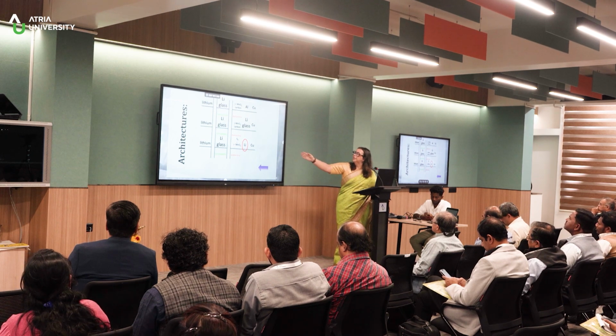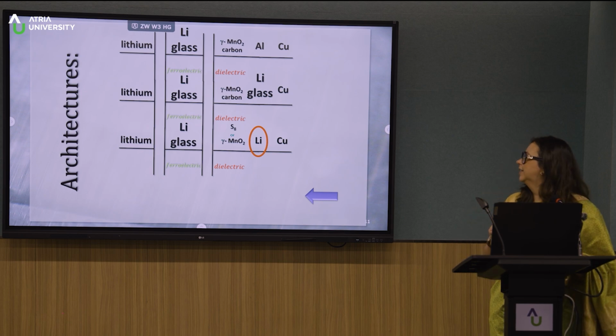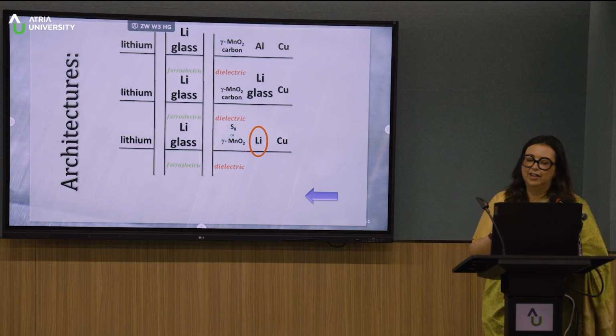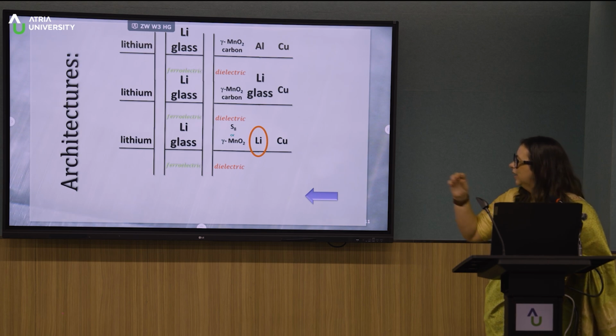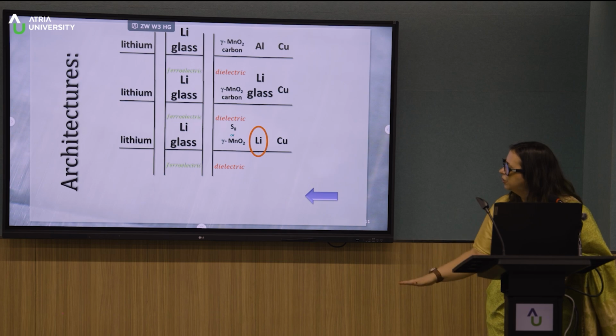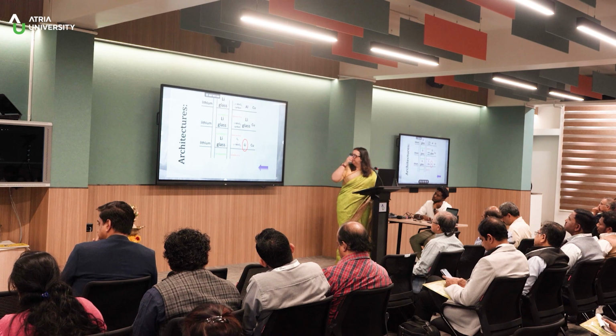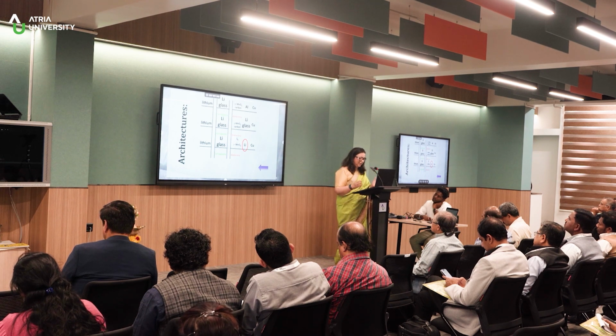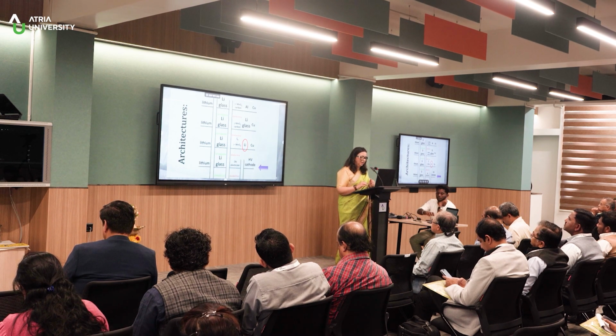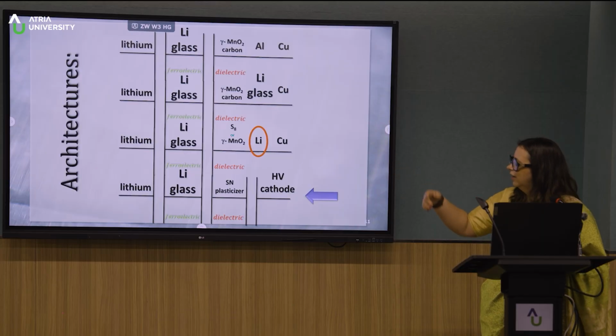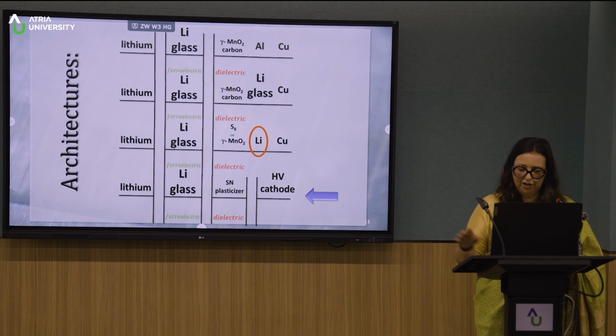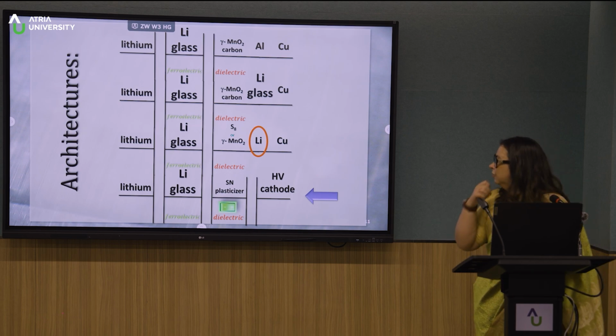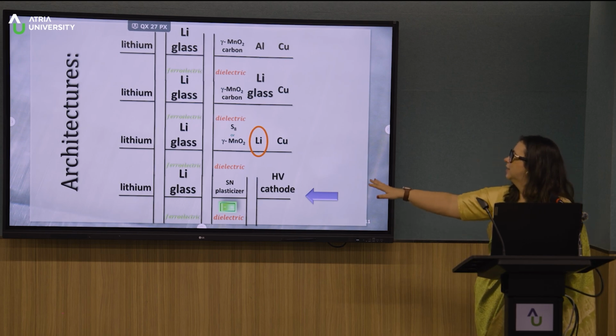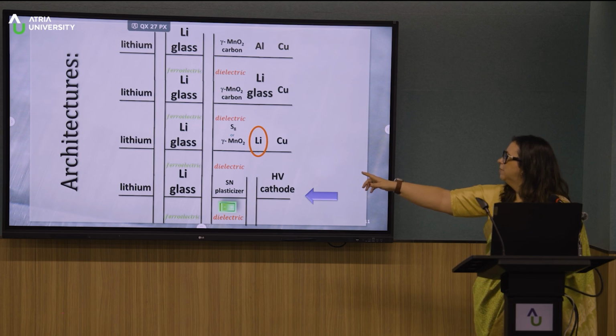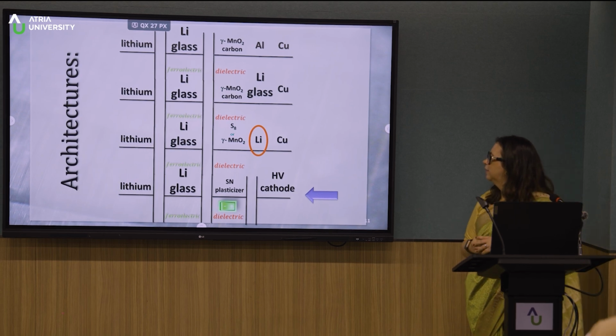If the electrolyte would see the lithium, then yes, we would have a symmetric cell. But because the electrolyte doesn't see the lithium, and the lithium can bring the chemical potential down in presence of copper and sulfur, then we have the same kind of cell that we would have if we didn't have the lithium there. And I'm going to show you in a moment the discharge of this cell. And we could also do some other cells where we put in the plasticizer, that is a dielectric material, in the middle of the electrolyte and the cathode.